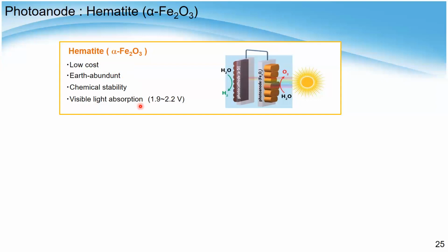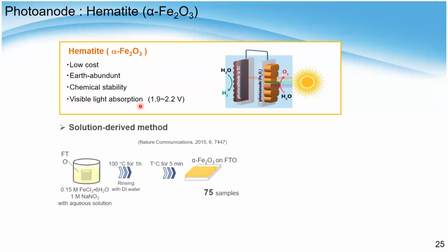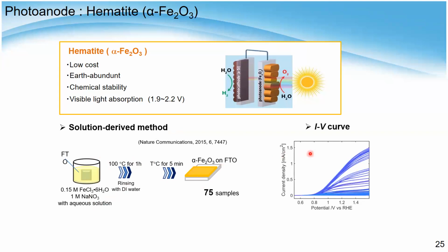So it has visible light absorption, and typically this material is prepared by a solution-based method. The conductive substrate is placed inside the precursor solution, heated up, and then coated on the surface. And this is evaluated by the photocurrent value versus the applied potential. At some potential voltage, the photocurrent is the performance value.